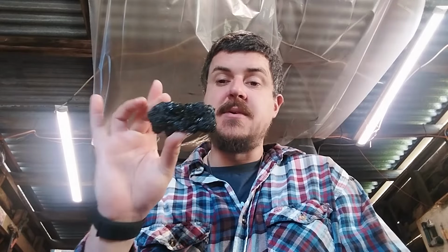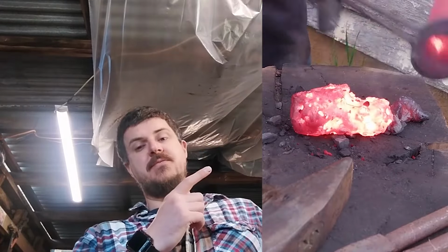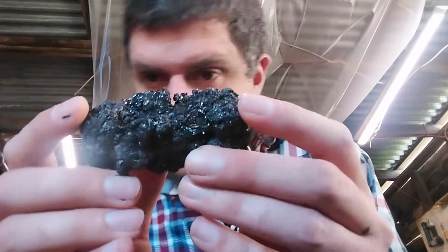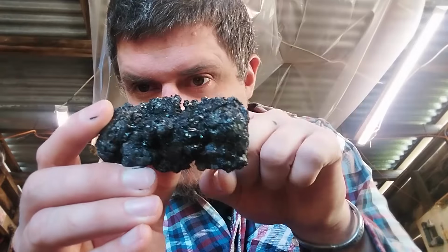But the other dialogue that will happen is that this is still going to want to fall apart because it doesn't really have any discernible grain structure, and it's very unevenly distributed in there. There's little pockets of carbon, there's little pockets of iron, there's little pockets of slag, and some parts of it are going to be slaggier than others. And you can actually see it when it first plopped out of the crucible. There's this sort of solid mass, the 2/3 on the left is very together, and then the very far right is very together, but in the middle connecting them is a very sort of soggy bit. That was because there was more slag in that bit than there was at either end, and you can kind of still see it on here right there.